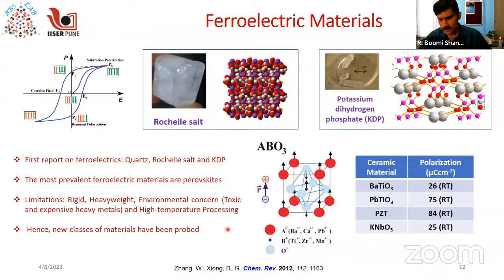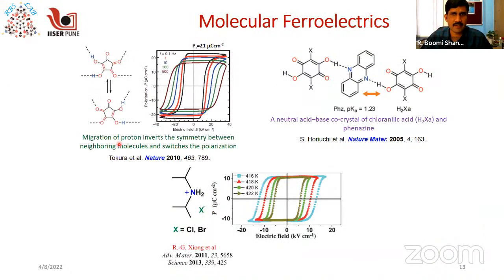Okay, so there are so many materials that are known, as I told you, the ceramics, but recently people started working on small molecule based ferroelectrics. These are some of my favorite examples. This is croconic acid, which exhibits a very high polarization of 21 microcoulombs per centimeter squared, which is very close to the polarization of barium titanate. The proton tautomerism was found to be responsible for the reversal of polarization in the system.